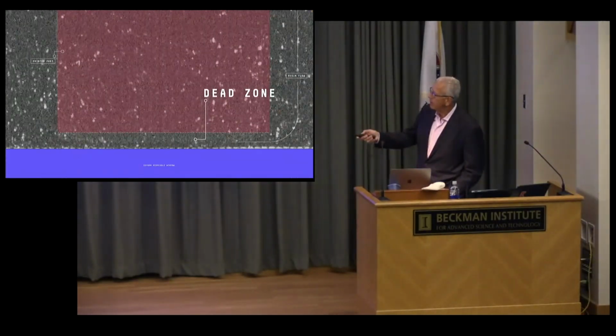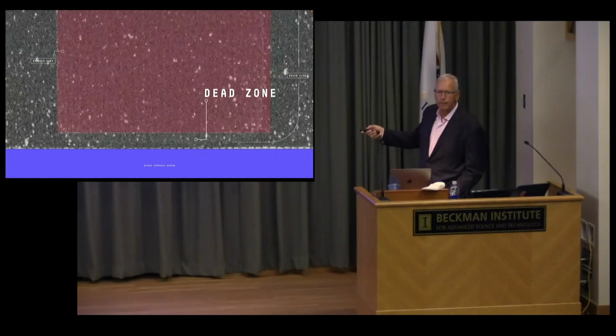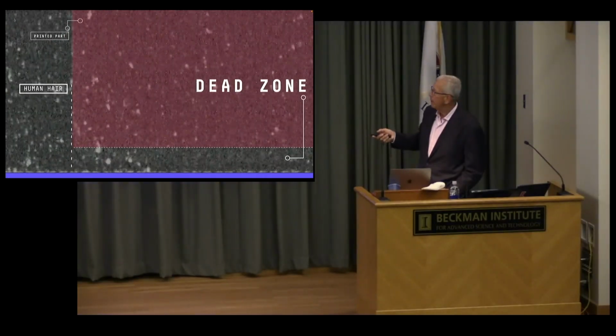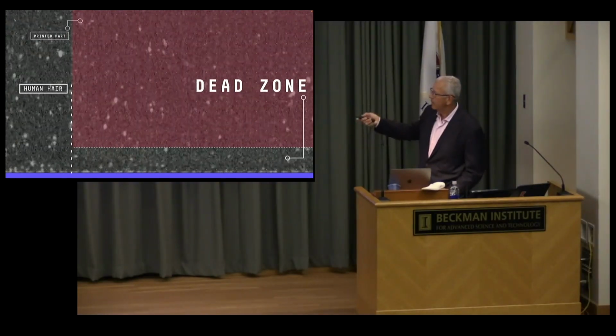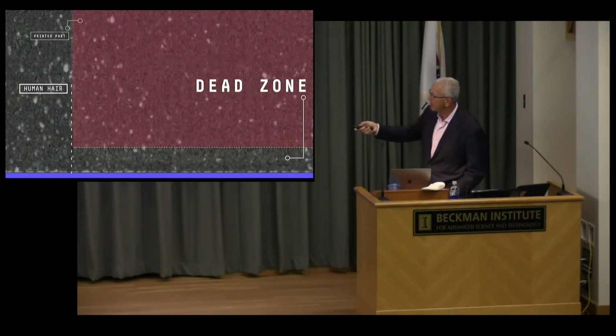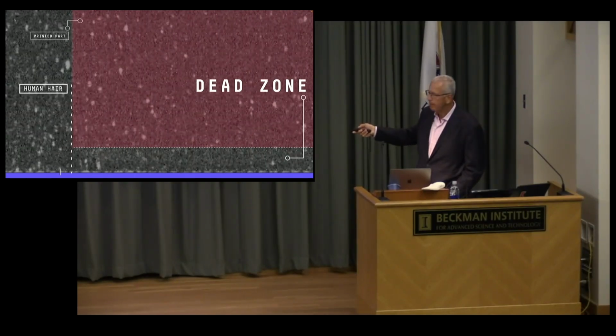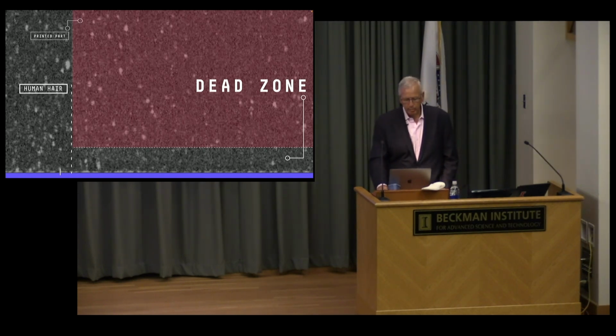And you see the resin being drawn into this gap as we elevate the part. It's just caused by the negative pressure pulling the resin in. And this allows resin to be renewed at the build surface. This gap is created, well, first of all, this mauve color, the polymer, is being created by light. The resin's got a photoinitiator in there that decomposes and creates radicals, but it doesn't polymerize in this zone because oxygen's replenishing. And so let me explain that in a little more detail.